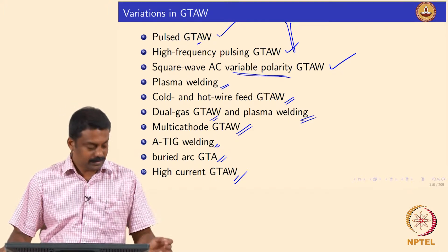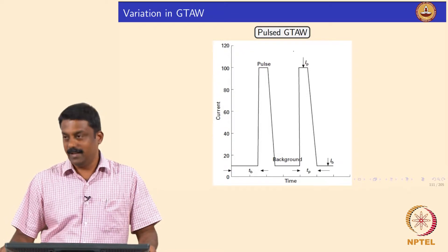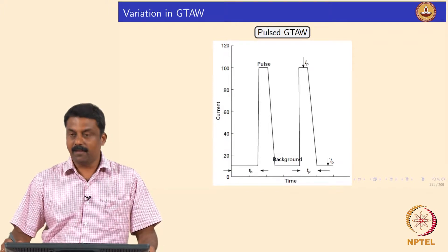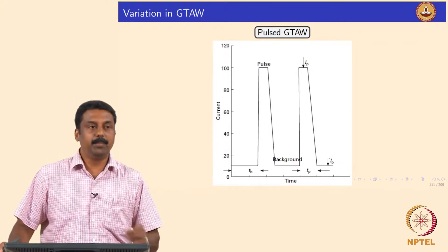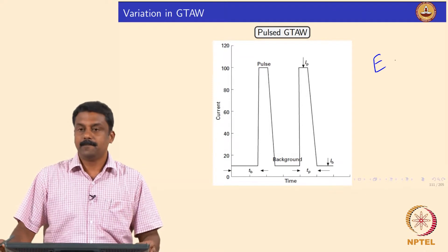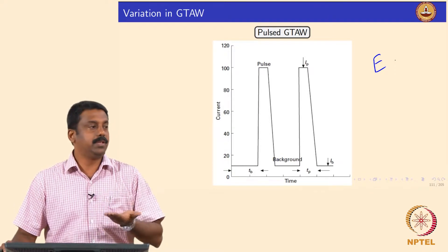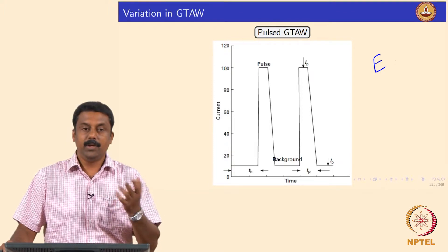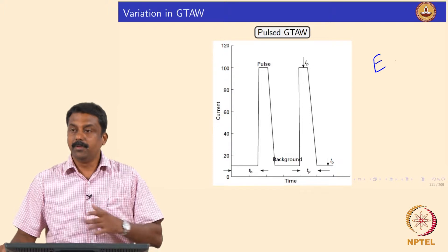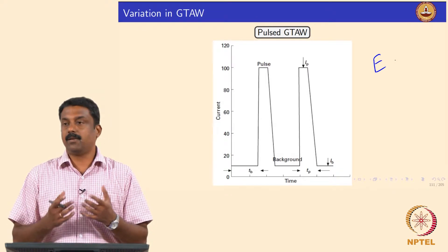We will see the first two in this class and then move on to the next chapter. So, pulsed GTAW — why do you need it? In pulsed GTAW you do not use a constant current; instead, you pulse the current as a function of time. This is beneficial because having a pulsed current rather than a constant current improves arc stiffness tremendously. By pulsing, you also constantly change the electric field E, which means the acceleration and the mean free path of electrons and ions also changes. When you continuously change the input, the arc stiffness and the arc core temperature change significantly, increasing the number of electrons colliding and the number of electrons generated because of those collisions.